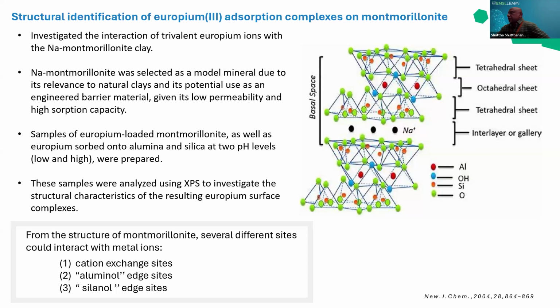So if you look at the structure of this montmorillonite clay, it has three different features. One is called aluminum octahedral, and silicon tetrahedral, and then you have the interlayer or the cation exchange in this layer here. So what is going to happen here is when you deposit this europium, it can go and interact in these three different states. So they studied with two different pH levels, low and high.